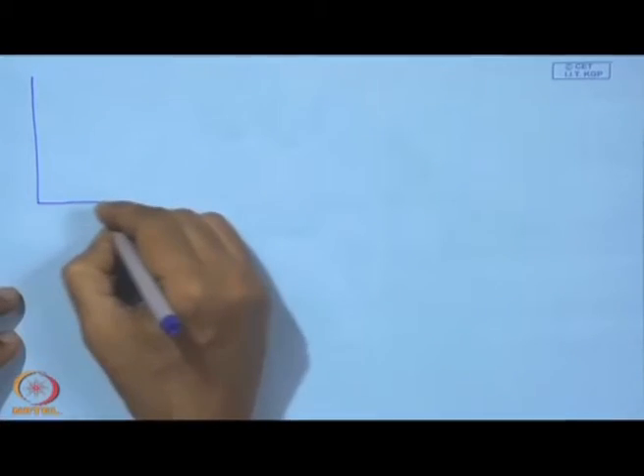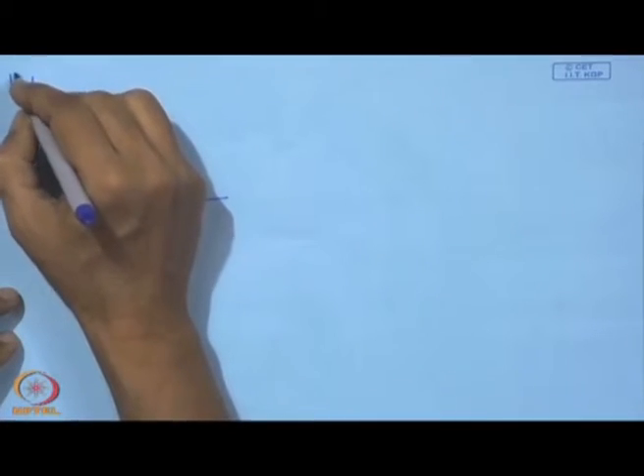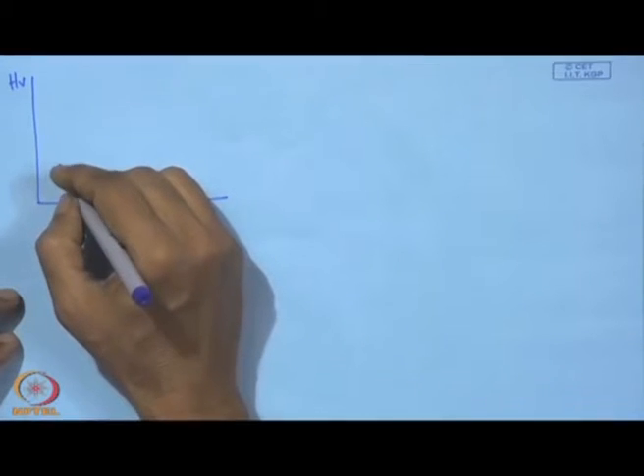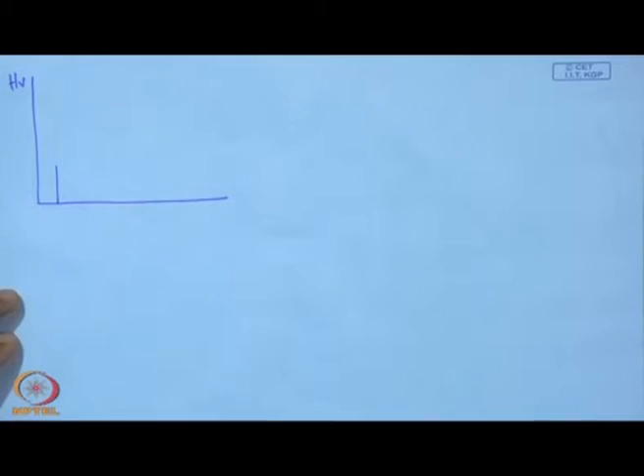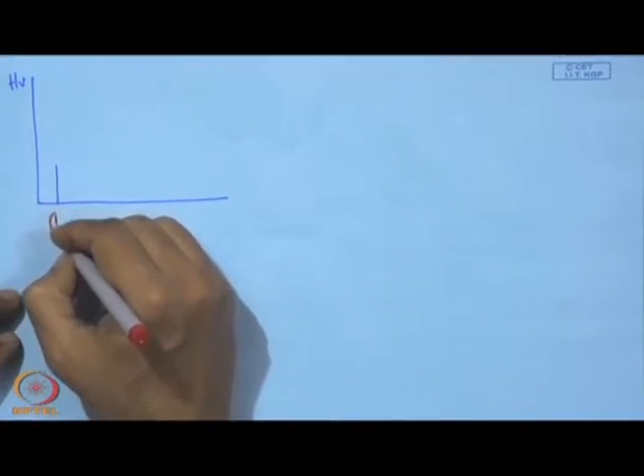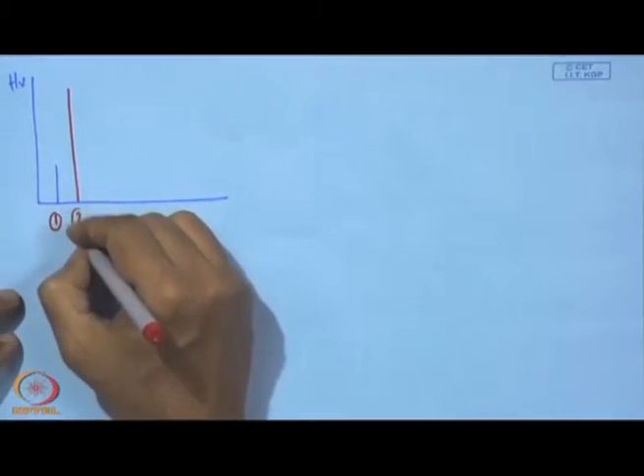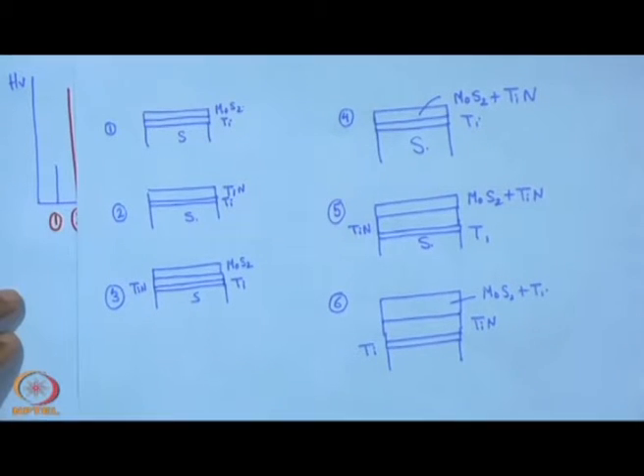That means, when we see the influence of architecture, we mean the influence of this architecture on the final mechanical properties of the coating. Here we can look into two things, first of all the hardness of the coating. This is hardness, HV, and on this we can have a hardness something like this for number 1, and then number 2 will be very high for an obvious reason, because number 2 has just titanium nitride, and titanium nitride is known for its hardness.